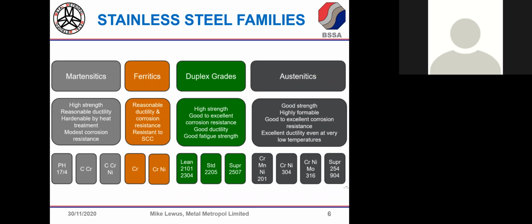Hidden in the martensitics there, at the bottom left, you'll see PH 17-4. Now, I often describe that as a separate family. In truth, the basic structure of the material is the same, but some of you may be aware that PH stands for precipitation hardened stainless steel. So there's a subcategory, if you like, under martensitics, which are a very high-end special group of materials that tend to be used in, well, they're certainly used in the marine environment, but particularly demanding market sectors, whether it's aerospace, power generation, marine, as I've already said.